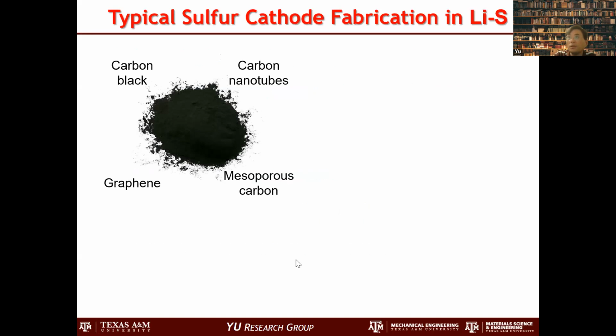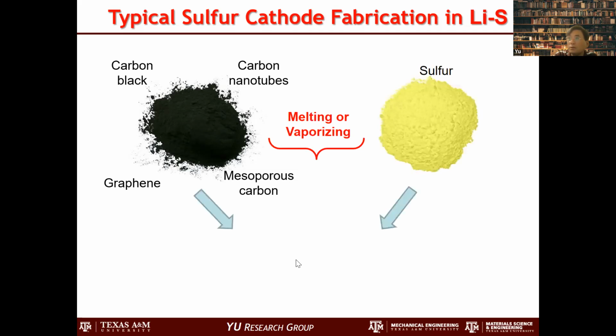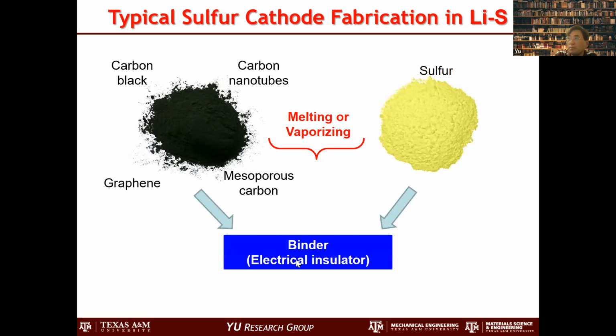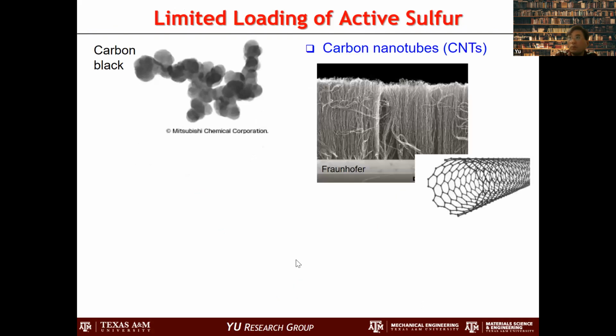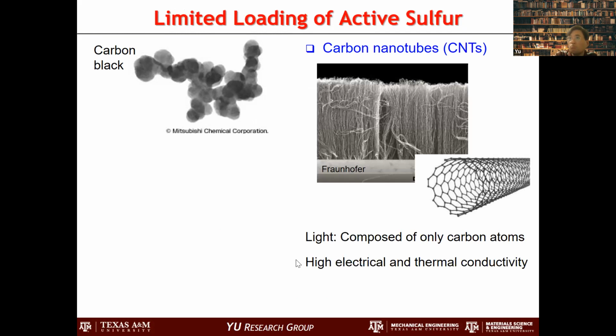Typically, when we make a cathode, we use carbon black or any carbonaceous material like graphene or graphite, whichever. We need an electron conductor, and then we use sulfur powder, mix them together, add a binder, and make a cathode. So that's typically what happens. Pretty simple. There's carbon black, and sometimes people use powdery carbon nanotube. Compared to carbon black, carbon nanotube is actually pretty good. Graphitic carbon in wire format is a pretty good electron conductor, so charge transfer is actually pretty good.